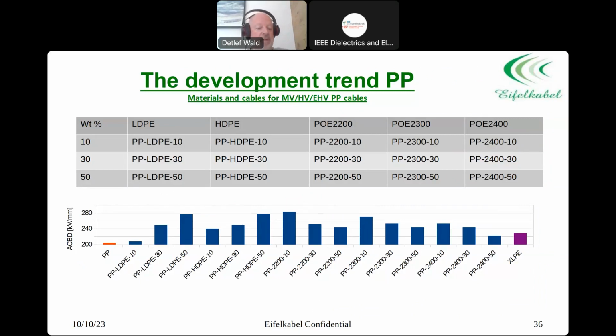Now looking more into the development, because naturally people are looking into the future. Here is an overview about polypropylene, and added to this different parts of LDPE 10, 30 to 50, high density polyethylene, same range, polyolefin elastomers, different ones, and then pure polypropylene, and on the right hand side you see pure XLPE. As you can see, by adding other materials to polypropylene, you can improve the electrical properties of pure polypropylene in the AC breakdown test.